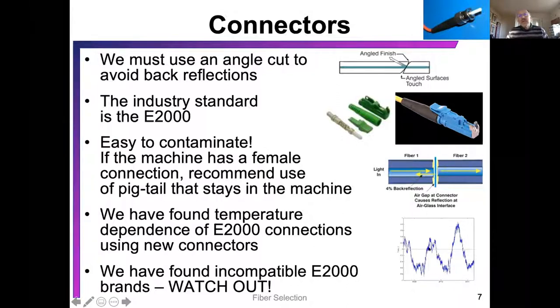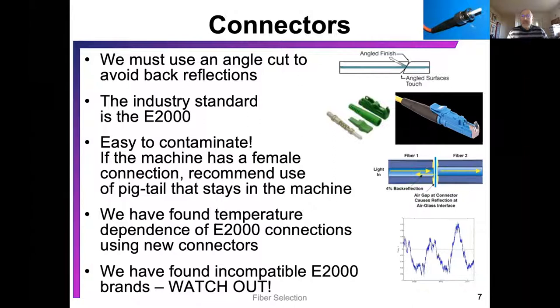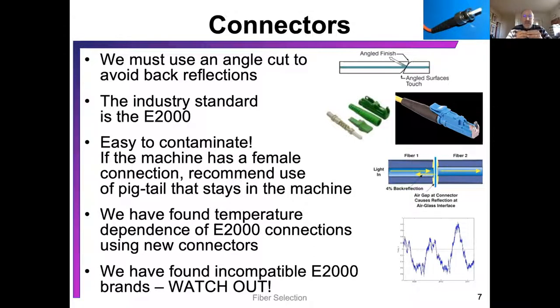The E2000s can produce a temperature artifact of up to 0.6 to 0.8 degrees Celsius at the connector when the plastic E2000 is heated and cooled. When you heat and cool an E2000 in a barrel connector, you get an artifact in time. The plastic has quite dynamic thermal properties, so changing the force of compression changes the transmission characteristics — we lose more blue light than red light, giving a temperature artifact at the E2000. Therefore: do not put E2000s after your calibration baths. From that point on, you must use fusion splicing.